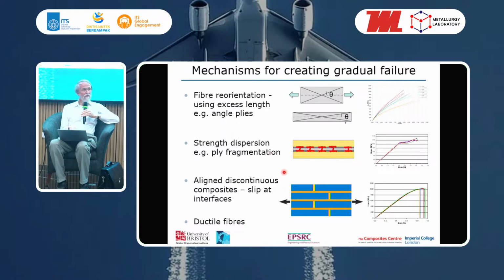We also looked at using discontinuous materials, where if you have discontinuous fibers, then you can have slip at the interfaces between the different materials, and this again can give you some non-linearity and a bit of pseudo-ductility. We didn't actually find that gave us a large amount of ductility, but it did produce a small change in the stress-strain response, as you can see on this curve here. So rather than just failing at this first point here, we've got a little bit extra with a bit of a plateau on the stress-strain curve.